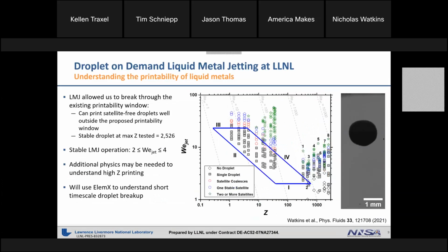Okay, we found that not only can we print stable droplets at high Z, but at a Z of over 3 times higher than the extreme corner of the printing window. So we essentially broke the window. We were able to print satellite-free droplets for all Z tested and found a stable operation range for jet Weber number between 2 and 4 for all metals tested.